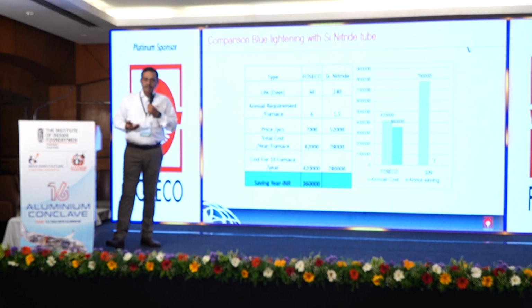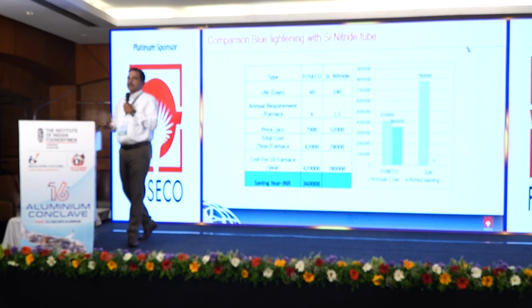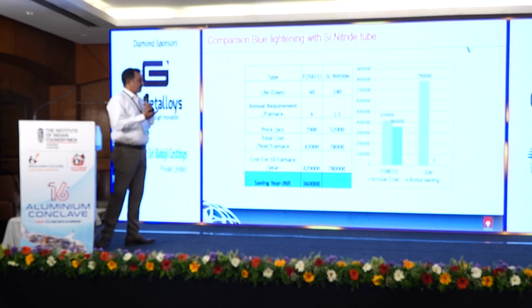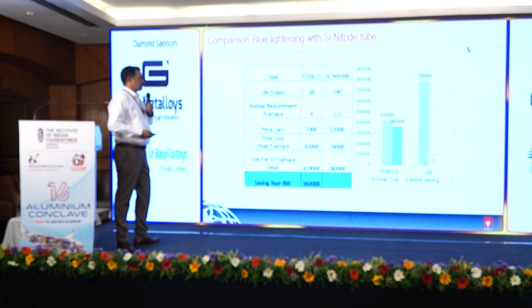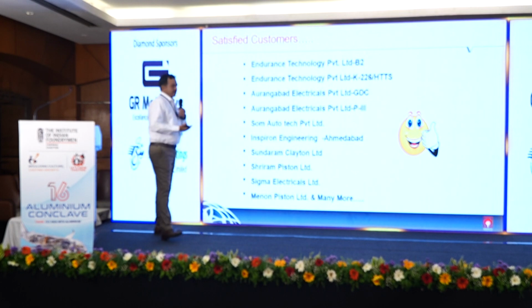And the same way, even silicon nitride is on the higher side, somewhere around 52,000 rupees. Although it claims that it gives about 240 days of life, more than half of the year. So if you compare, for 10 furnaces your saving is close to 3,60,000 rupees. Although the life is more in silicon nitride, comparatively for 10 furnaces the saving is close to 3,60,000 rupees.